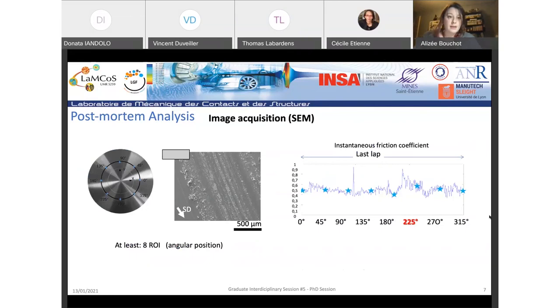The other aspect of postmortem analysis is image acquisition using a scanning electron microscope, SEM. For this, different regions of interest are selected, but you need to know that what we observe on the disk corresponds to the last lap of the test. It's important to know that because if you search for a specific event, you look at the friction map before. If it's not on the last lap, it's difficult to see it on the disk.